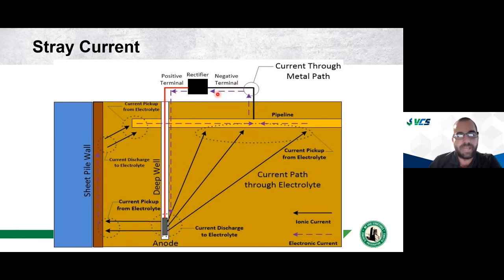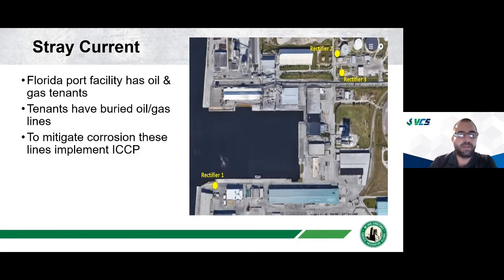Now, what was happening is, because this well was so close to the sheet pile wall, the current was also going from the anode to the wall, but it has to return from the wall back to the rectifier, because all current has to return to its source. So it's got to leave the sheet pile wall and jump back onto the pipeline to get back to the rectifier. And whenever you have current that goes from a metal to a soil or water, you get corrosion damage. Where this current was discharging back to the pipeline, it was causing damage. If we look back here, this rectifier was so close to the wall, it was picking up current and discharging it back to the pipeline, and that was causing damage to this wall.